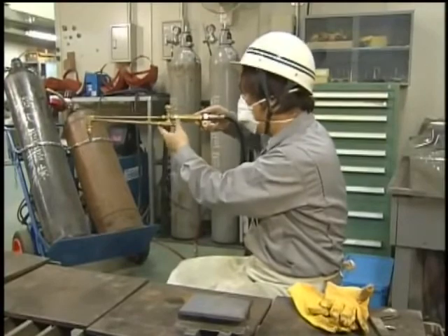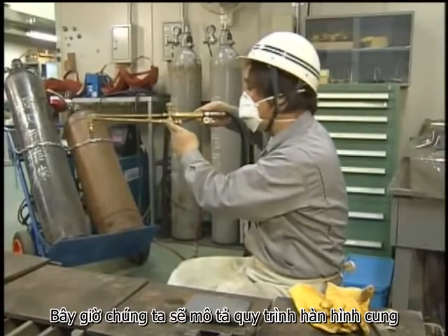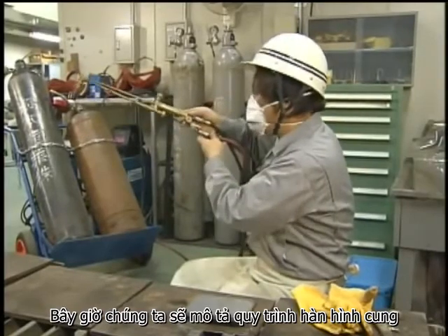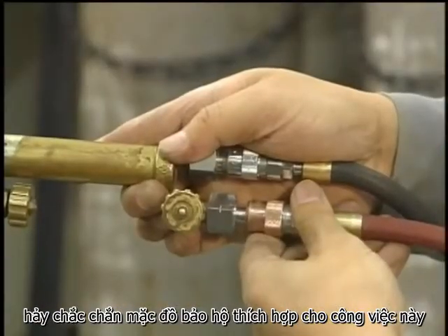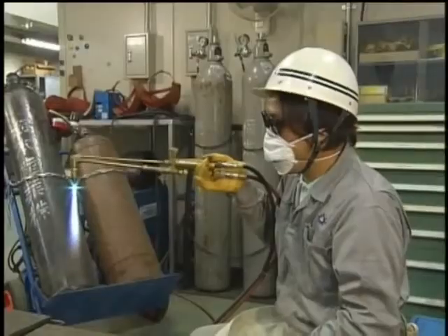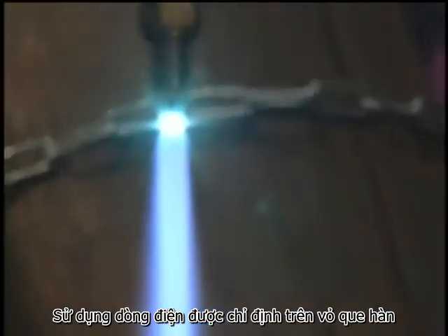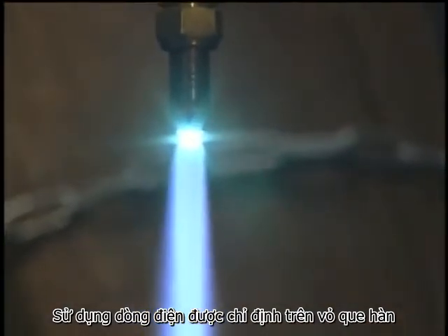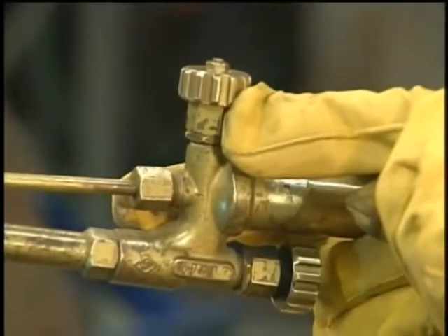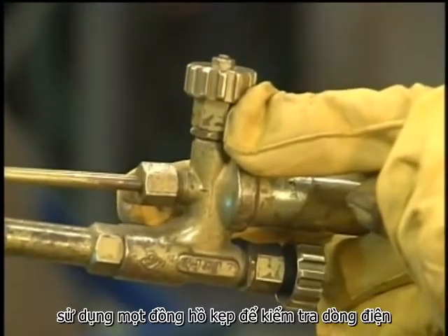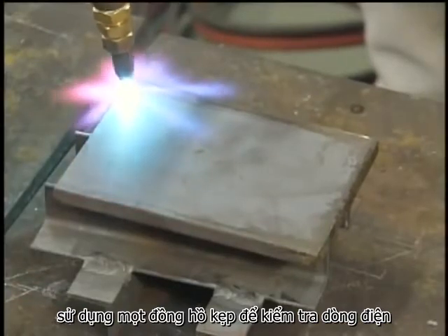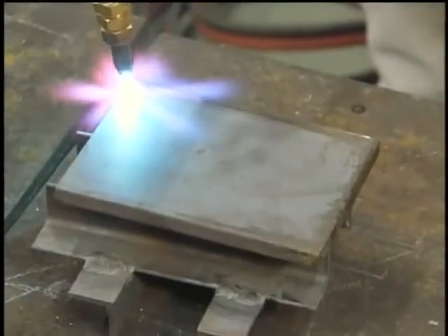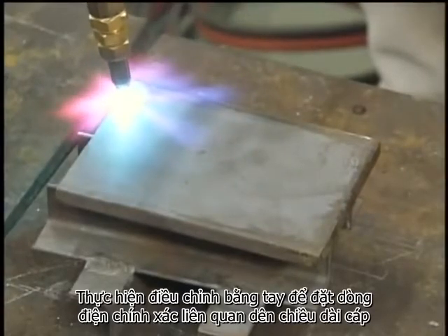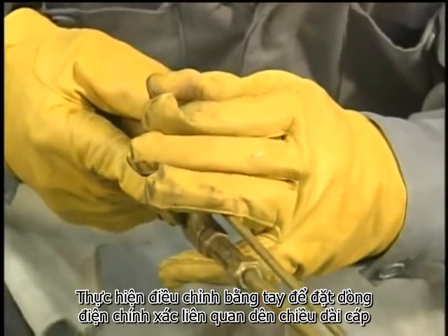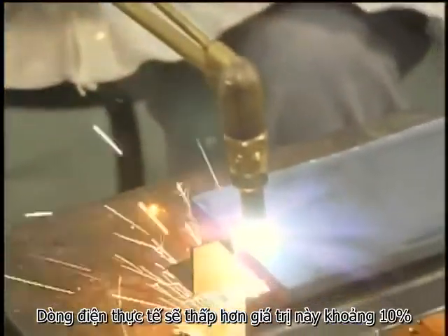This is a blowpipe used for cutting. Here also, check the action of the injector before fitting the acetylene hose to the cutting blowpipe. Adjust the flame so that the flame core looks like this. This valve provides the oxygen for cutting. Leave a gap of about 3 millimeters between the tip of the flame core and the base metal and preheat the base metal. When the base metal is red, open the oxygen supply and begin cutting.